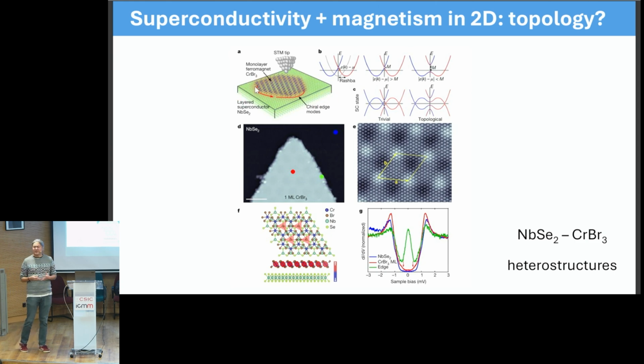So this is all done in an ultra-high vacuum environment. And then they do an STM experiment. Essentially with STM, they can go to these islands here, which are magnetic, but are in proximity to a superconductor. And they do scanning tunneling spectroscopy, and they see zero bias peaks, which they then conclude are due to topology.